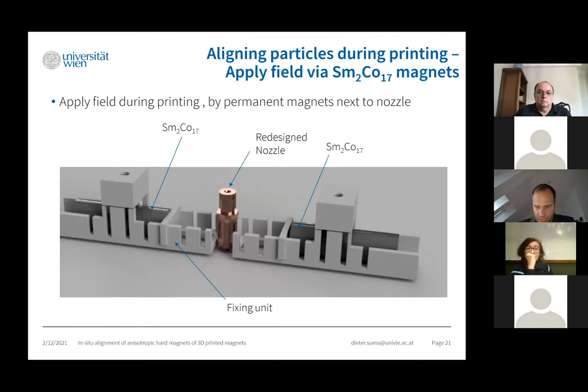We now tried to align them during the printing process, and we did it the following way. We placed next to the nozzle permanent magnets, samarium cobalt permanent magnets. We chose samarium cobalt because of its ability to be resistant to heat. And we built the fixing units in a way that we could easily change the distance of these samarium cobalt magnets. This was important because if the magnetic field is too large and we have a too large field gradient, we can't print successfully anymore, and the magnetic fluid is not positioned on the building platform, but sucked to the poles of the permanent magnet.